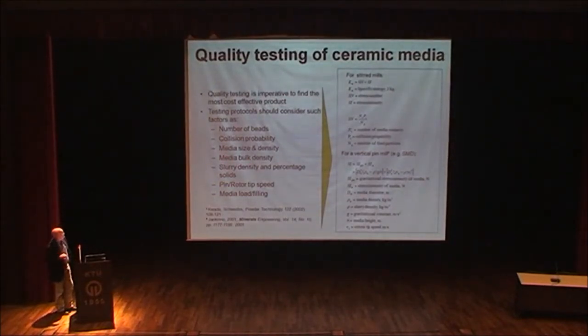Bulk density of the beads, slurry densities and percentage solids, the tip speeds, media, the load filling, what sort of load you put in your mill. You can put in an 80% charge, you can put in a 50% charge. Sometimes 50% will give you better milling, better performance, lower energy than an 80%. So these you have to take into consideration.